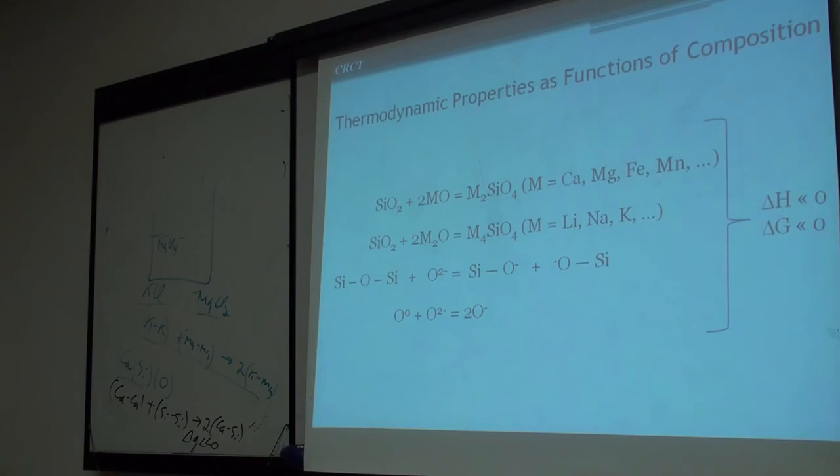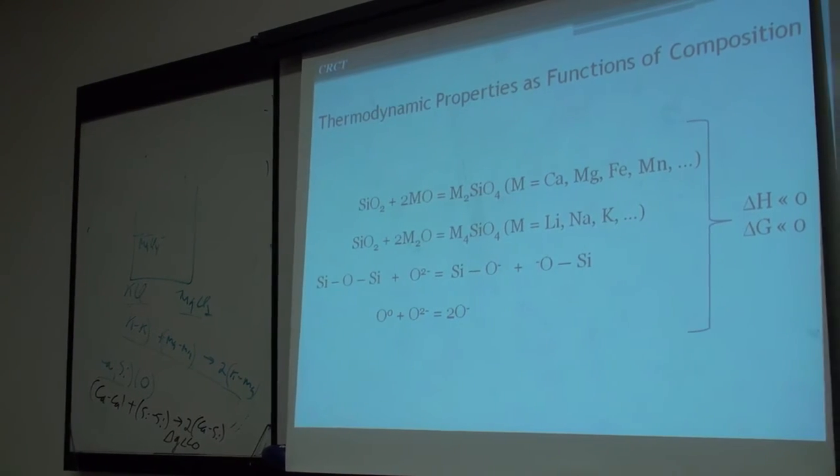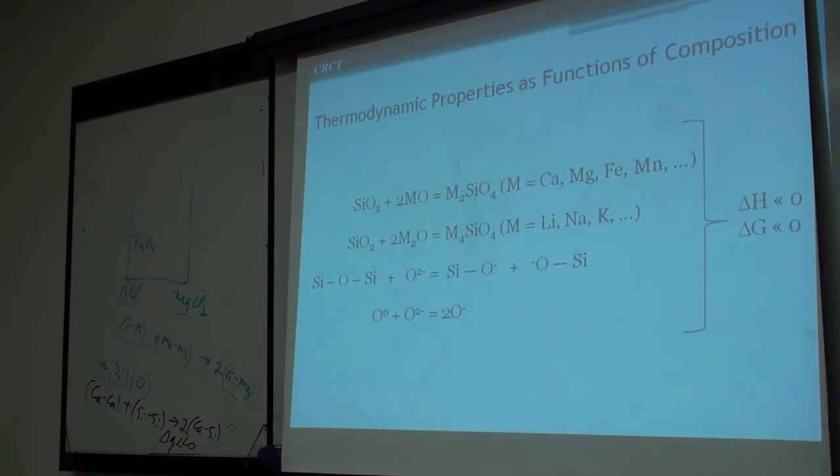So right back again, although it's a very complicated system, we're using the same one sublattice quasi-chemical model that we use for something like aluminum-calcium, where you have your Z ratio. Now in the calcium-silica it is again 2:1, because you want the minimum at 33%. Sodium silica would be 3:1 because you want the minimum at Na4SiO4.